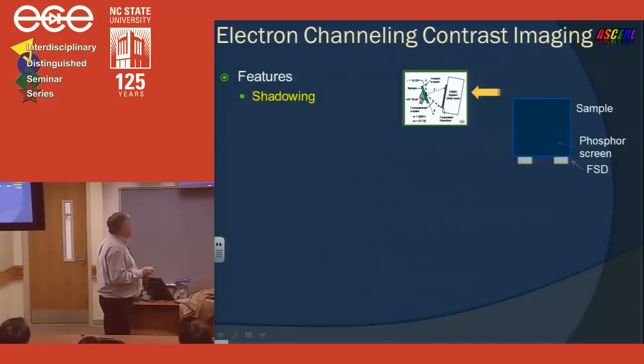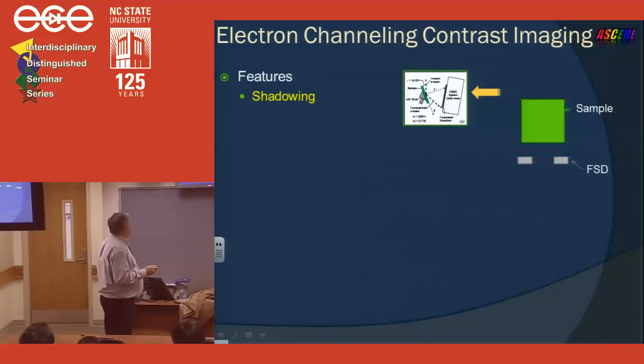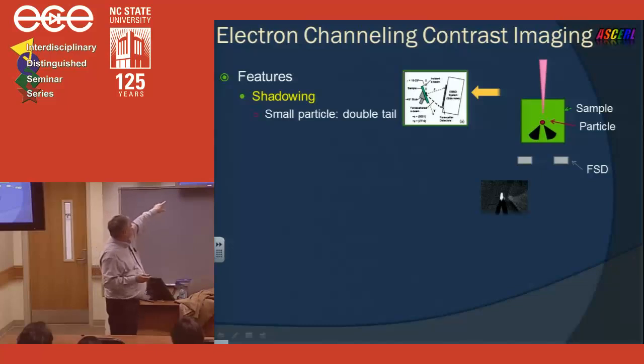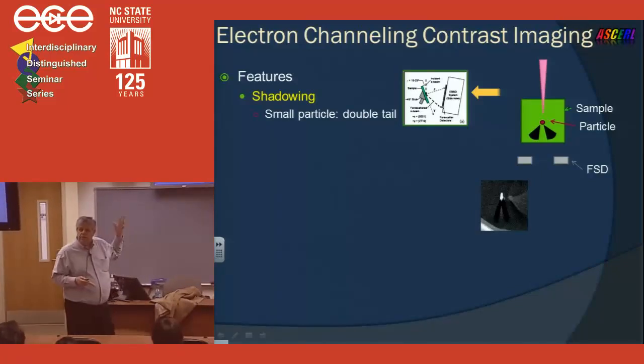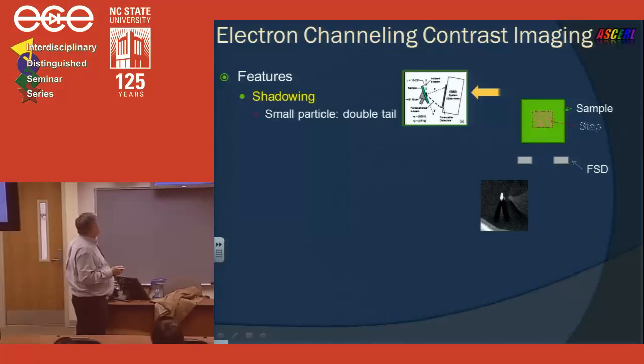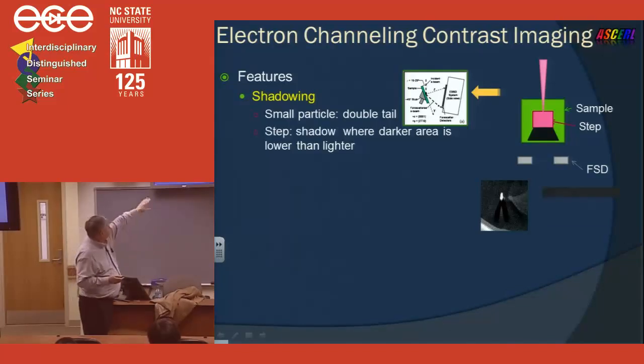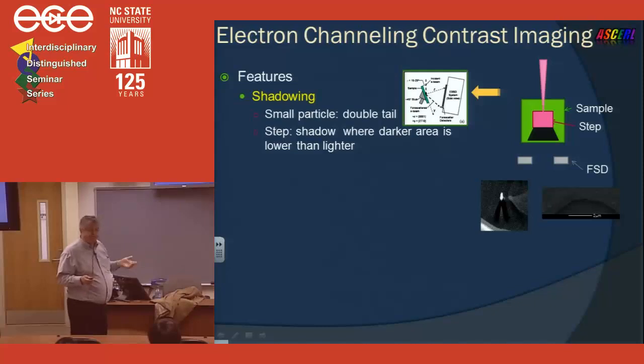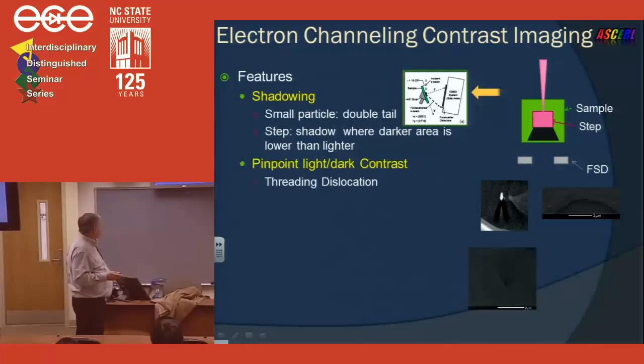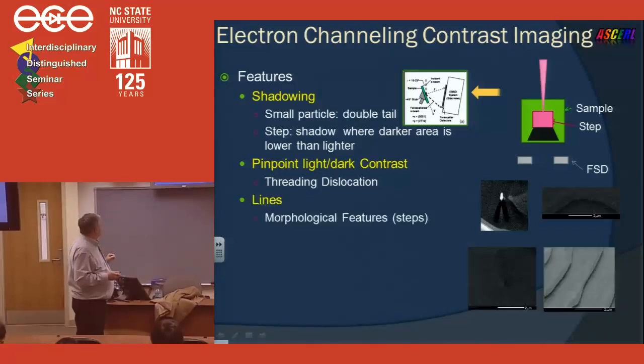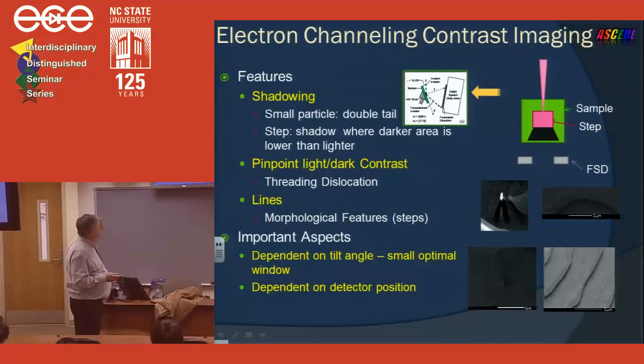So ECCI is good because you take your sample, you take your forescatter detectors. Suppose you had a particle on the sample. We have the electron beam, and it comes through, and it looks like it creates a shadow. So that gives you that three-dimensional feel in the SEM image. Likewise, if I had, say, a step on a sample, and again the electron beam comes through, the image shows a shadowing. And so you get a three-dimensional feel for the step. And that's the power of it. Normally, if you just use SEM in its regular mode, you just get a flat planar image. So if we have a point-like defect, what happens is you see a contrast of light and dark, and the contrast is the key to identifying the source of the dislocation.